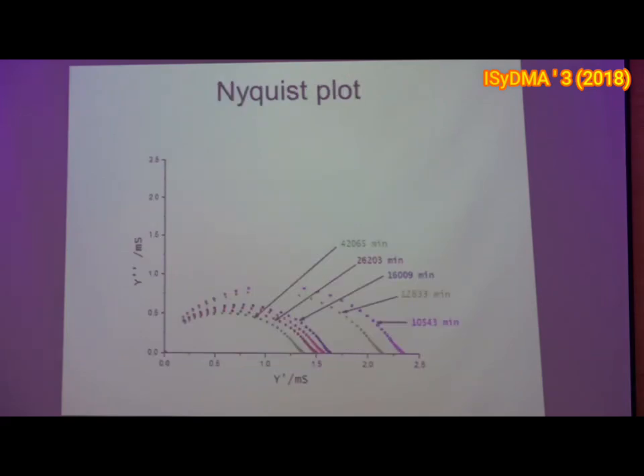So this is again the Nyquist plot. I can see the circles, different circles for different moments. I always see this relaxation process, and then I can calculate, for example, where the resonating frequency is as a function of the time of cure.